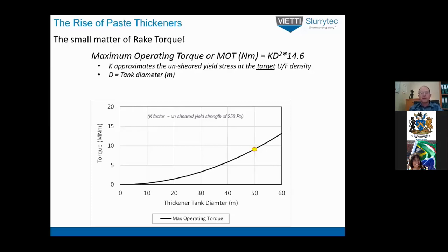Now, in paste thickening times, the K has been replaced by the approximate unsheared yield stress of the underflow at the target underflow density that's required. So you would go into the lab, measure the unsheared yield stress of the material at the target or design underflow density, and that would effectively be K. In the bottom graph, I've shown the torque requirement, in million Newton meters, against tank diameter, assuming a K factor of an unsheared yield stress of 250 pascals. So for a 50 meter diameter paste thickener, you require something close to 10 million Newton meters. That's what has been known as the maximum operating torque.